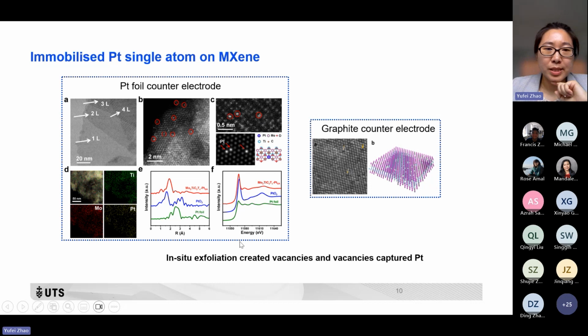For the XAS result here, we can see our catalyst shows one dominant peak here between 1 to 2. That means the platinum single atom has been stabilized by the light atom, and also the XANES results show the valence state of this platinum is between the platinum foil and the PtO2. That means the valence state should be between 0 to 4.